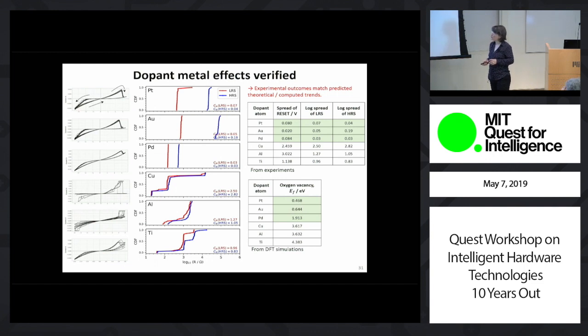So we cannot control the number because you are implanting more than just one path, right? So you are milling the edges, and whatever is implanting from the edges in. But it's possible that their properties are similar. So as we are switching and re-switching, I don't think it's guaranteed that we are switching with one filament only. But say gold or palladium, platinum are so distinct from the base material that they may be switching similarly, even if it's not one filament each time.